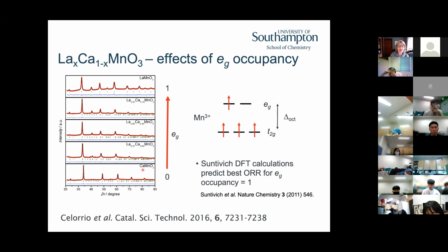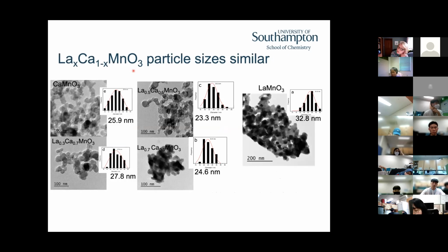And we can show that we can make the whole series of samples as we go from lanthanum manganate to calcium manganate. In the calcium manganate, the EG orbital is unoccupied. Well, in lanthanum manganate, the EG orbital is occupied, right? And so we're seeing this range. So here are just the TEMs to show you that she's got really nice, pretty small particles. Now, as someone who started off with metal nanoparticles, which I can have between 2 and 5 nanometers, these seem pretty large to me, but they're not the bowling balls that you get from some of the other methods, hundreds of nanometers in diameter.